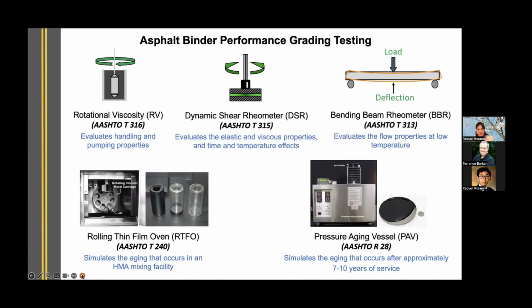And here I will show you the testing apparatus for each one of the properties that was previously described on the previous slide. For rotational viscosity, we use a Brookfield rheometer, and the test is performed in accordance with AASHTO T316, where we evaluate the overall handling and pumping properties. This is an important property that we always consider evaluating, especially when we have additives, because we want to see how the workability of the binder is after the incorporation of the additives, and if this would change what is expected as a common behavior in a plant.